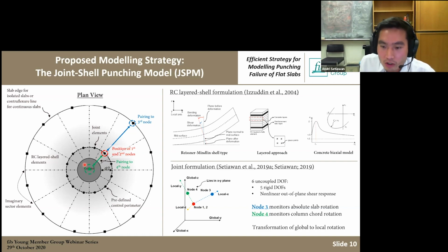Also, node 3 and node 4 are required to do a transformation of the global rotation, because in finite element, the rotation that we get normally is rotation in the global direction in X and Y. But in this scenario, we need to transform that into a radial rotation, which is basically the rotation that controls the opening of the tangential crack. So we need those two nodes also to transform the rotation.